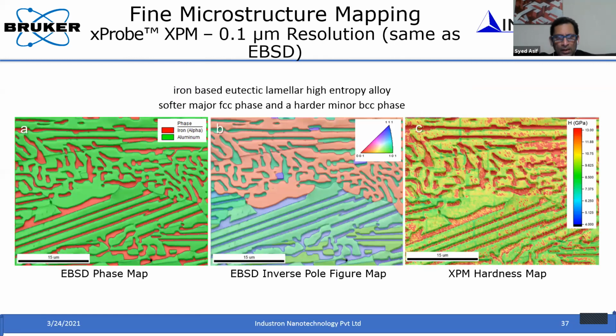This is another example. This is for a high entropy alloy, an iron aluminum based high entropy alloy. You can see, again, the EBSD phase map and the first image showing the distribution of the iron as well as the aluminum. And then you can see the crystallographic orientation in the IPF map of the EBSD. And if you compare the hardness map, it completely gives you the contrast at different regions. This is a high resolution hardness map, as good as your EBSD or a phase map that you can get with the EBSD. Okay, so this is very important because now you have a direct structure property correlation down to this crystallographic scale.